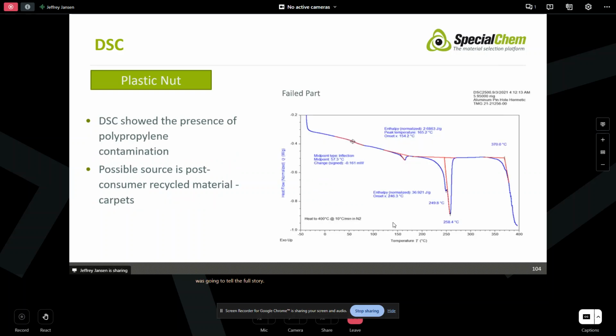DSC though gave us some additional information, and that showed the presence of polypropylene contamination. And that, again, here's our transition associated with the nylon 6,6. We see this additional endotherm associated with the polypropylene, which tells us it is contaminated.